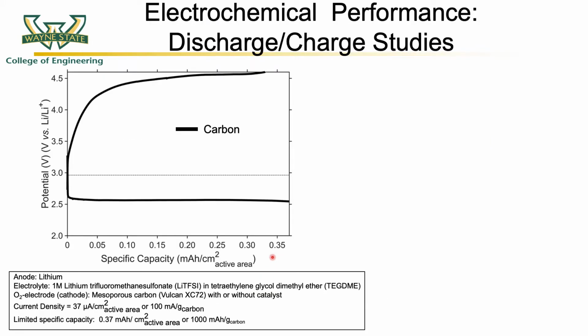The synthesized oxides are then incorporated into a lithium oxygen battery to study their electrocatalytic performance. Carbon is initially benchmarked by discharging and charging it to a limited specific capacity to gain insights into the near surface growth and oxidation of these species.